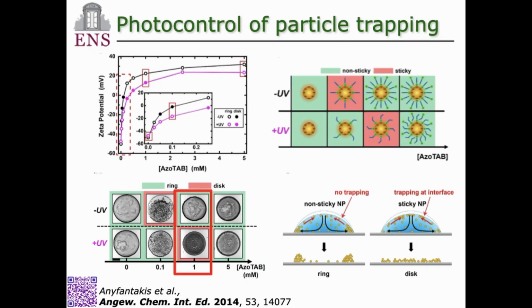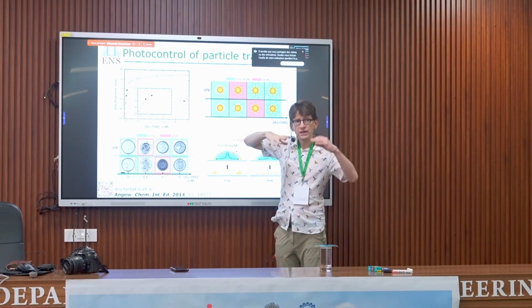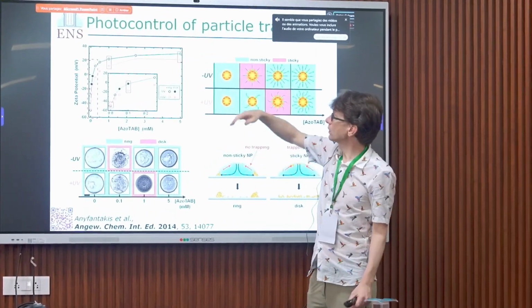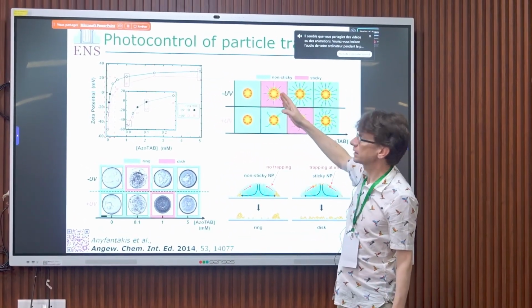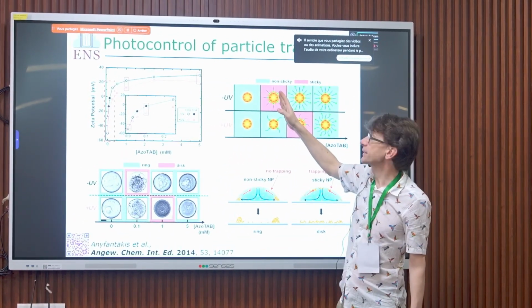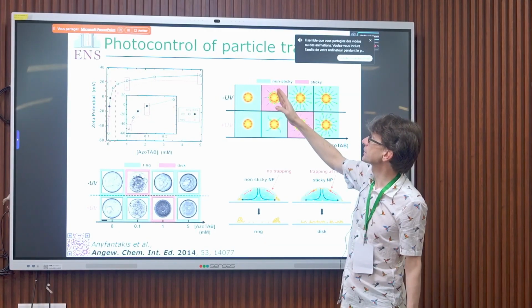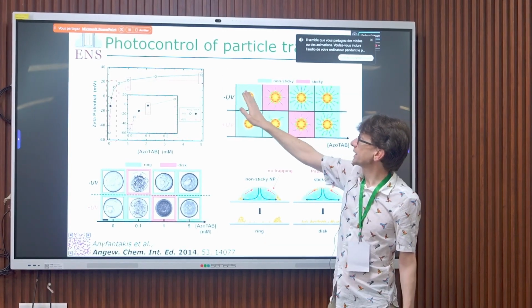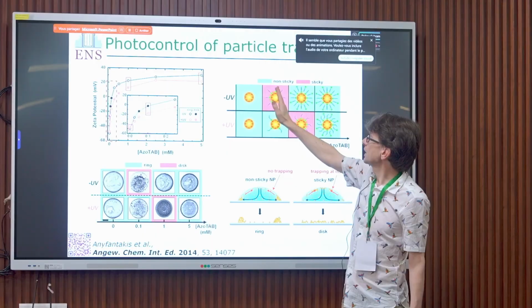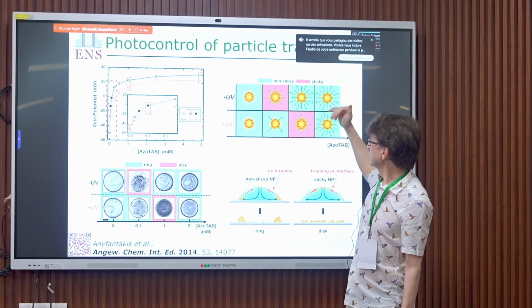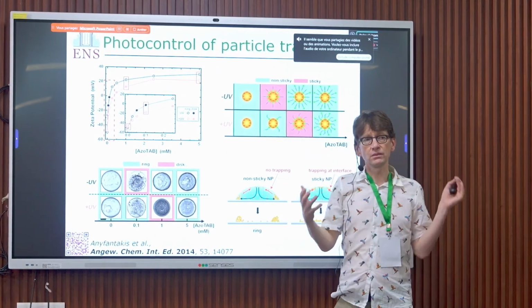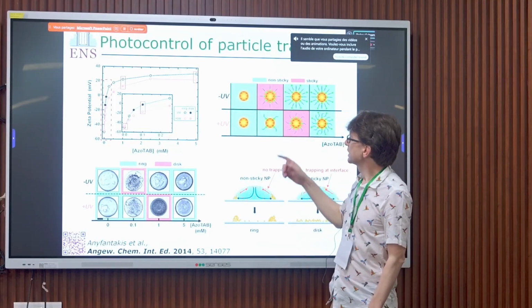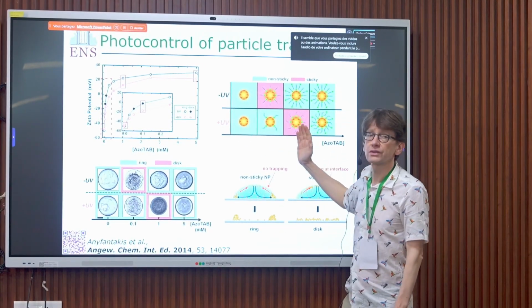And this is indeed what we have. So you see that without UV, my surfactant is more hydrophobic, so I will assemble more easily to the particle, so I neutralize at lower concentration. So I go to particles that are charged, neutralized, and overcharged. And if I do it with UV, since my molecule is less amphiphilic, this self-assembly will occur at higher concentration.